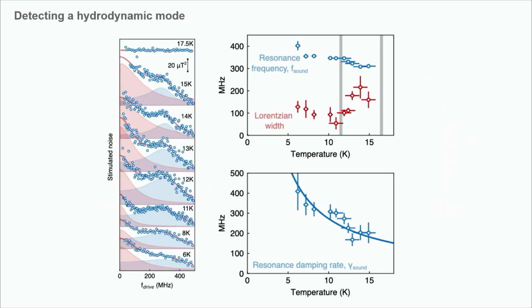But what you can do is track how this spectrum in the sample evolves as a function of temperature. This resonance frequency is basically totally unaffected by the transition to an interlayer antiferromagnetic state. It totally doesn't care about the interlayer arrangement of spins. We think that it's confined to the ferromagnetic layers. If you're interested, this Lorentzian tail appears to exhibit a sharp inflection point at that transition. So there may be a very slow interlayer spin hopping process that exhibits a critical slowing down at that transition. But for the most part, we focused on the behavior of this resonance.